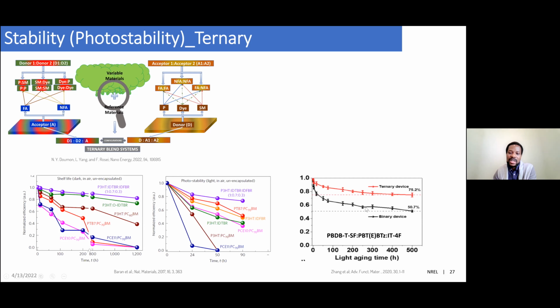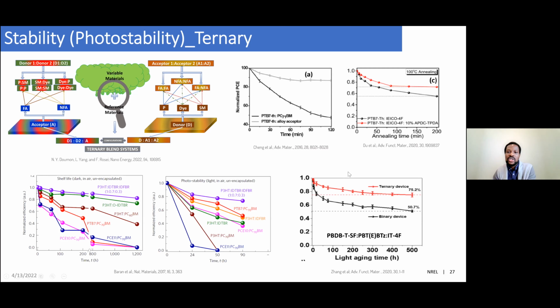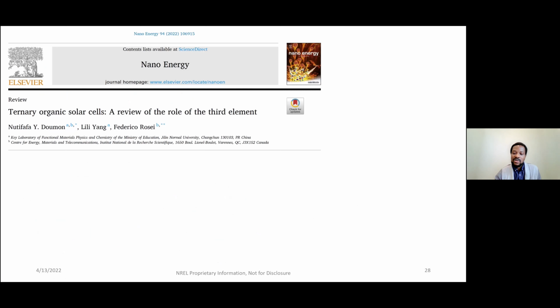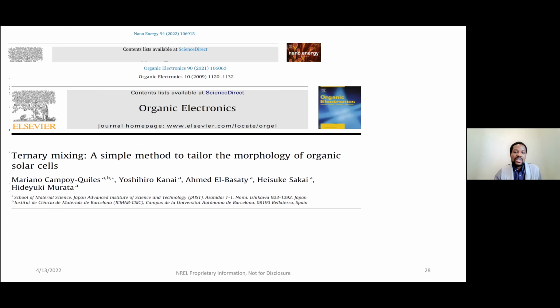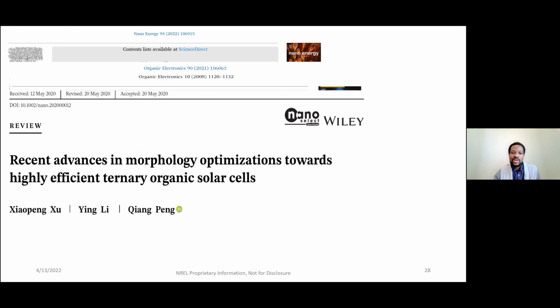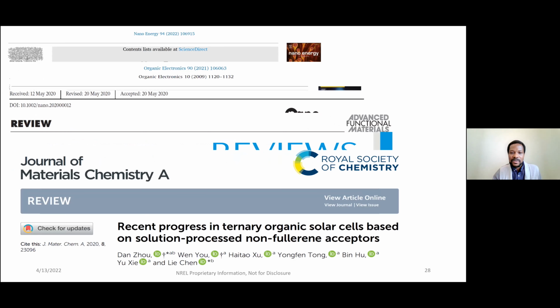Zhang et al. also show similar effect, but this is in control environment where ternary blend outperform the binary blend under light stress. And then when you go to thermal degradation, also other groups, Cheng et al. and Du et al. also show that, of course, ternary blend can be a way to improve the thermal stability of these devices. And then this also has opened a lot of door for the ternary blend system for a lot of studies, which are nicely captured in this set of reviews. And reviews are a good way to capture all the work that has been done over the years.